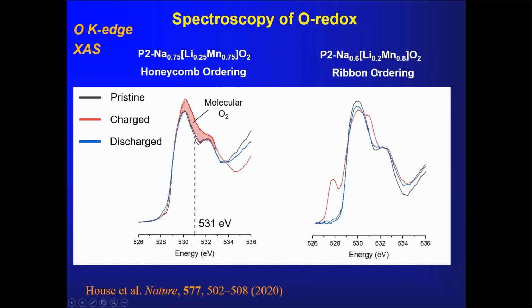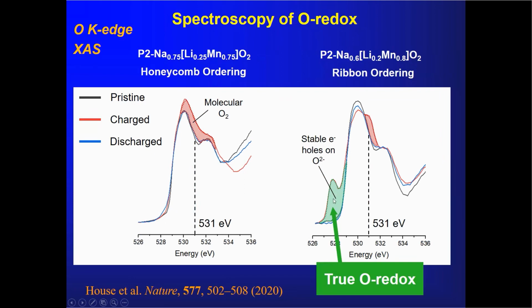In the case of the ribbon structure, you see a new feature here at about 528 eV. And this is the first real, I think, evidence of true oxygen redox. These are hole states on oxide ions, which are reversible. There's a small amount of molecular oxygen as well, as I mentioned, but this is the feature that I think is another signature for this changed behavior. And I think I should draw this to an end really with this slide here.